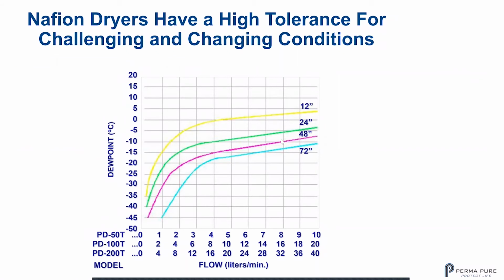I'll show you again how Nafion dryers have a high tolerance for changing and challenging conditions. Let's take a look at the green curve. That's a 24-inch dryer. And let's say we have a PD50T. So this is the top line of the performance. Let's say we're at 5 liters a minute. You can see that at 5 liters a minute, you're getting to a dew point of roughly -8. But what happens if your flow rate goes up to 8 liters a minute? Well, your dew point goes from -8 to -5, not that much of a difference, right? There's a high tolerance, and that's equivalent to doubling the amount of water in a sample. In fact, you can go to this 10 liters a minute number at the end. Your dew point is still -4.